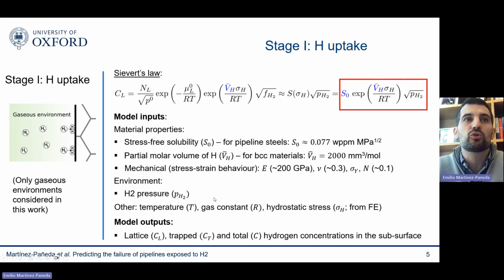And then what are the model outputs? Well, the lattice hydrogen concentration in the surface of the metal. If you combine this with a trapping model, as I will discuss in the next slide, then you can also get the trap and total hydrogen concentrations in the subsurface. And there's a bit of discussion about the applicability of Sievert's law, but I think it's mostly a misunderstanding. It's related to the fact that, of course, when you measure hydrogen uptake, you typically measure the total hydrogen concentration. So you need a trapping model to distinguish lattice and trap. But for lattice hydrogen concentration, this is a well-established and rigorous expression.